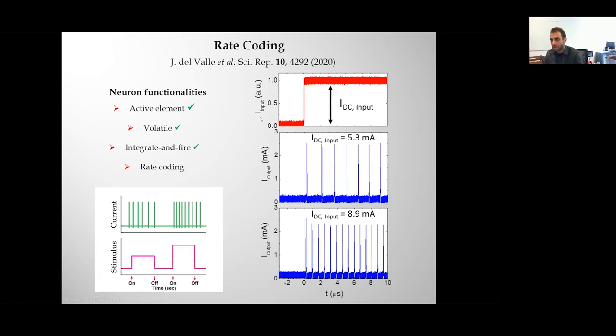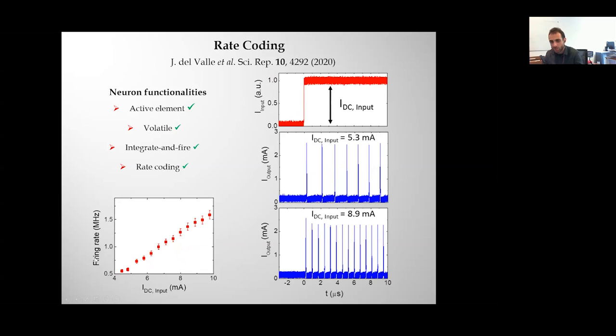Here you have current as a function of time, and here output as a function of time for two different inputs. So we send a DC input, with different amplitudes. You can see that when the amplitude is 5.3 milliamps, we have this spiking, but if we increase the amplitude of the input, you have a much faster spiking, which would be rate coding. And here you have the firing rate as a function of the DC input, and you see that we have this clear rate coding characteristic.